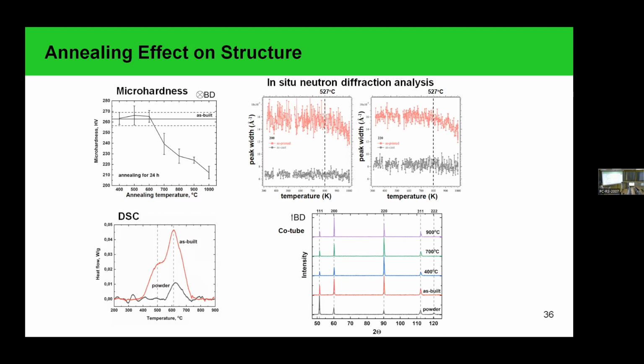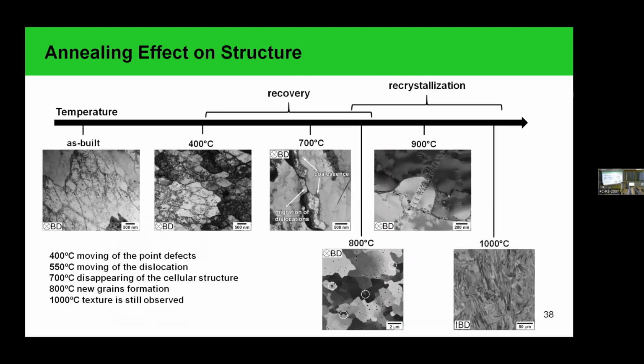And we also observed that even after such high-temperature heat treatment, like 900 degrees Celsius and higher, there is still texture along the build direction, and the structure is not fully recrystallized. So according to these results, there are several temperatures which can be indicated in the structural evolution of our materials. In the as-built state we see the cellular structure surrounded by dislocations. Starting from 400 degrees Celsius, we can assume that the point defects start moving, or it can be associated with the recovery of the point defects.